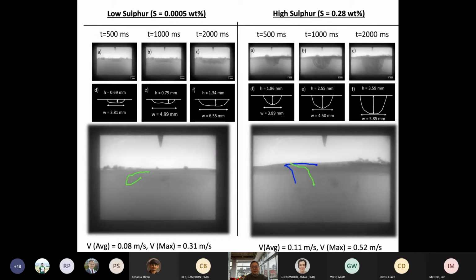Now we look into two levels of sulfur in our study. Starting with the left-hand side is the lower one, and the right-hand side is higher concentration. It's very high anyway, but we want to see this actual effect. The transition point should be very low between those two, but we chose those two. This is quite an arbitrary level of sulfur, but we want to demonstrate the effect of a surface tension change on the weld pool.